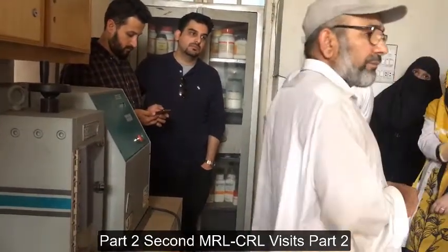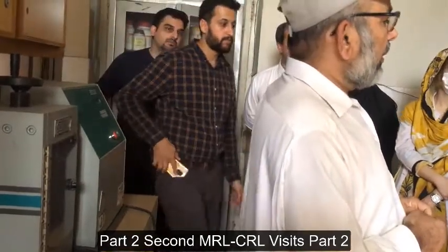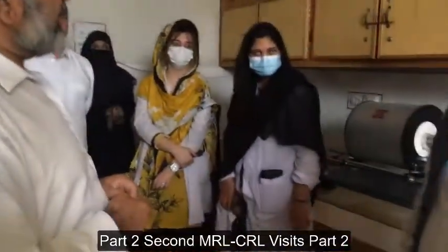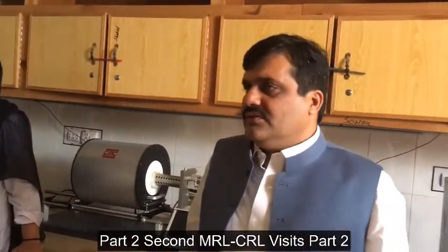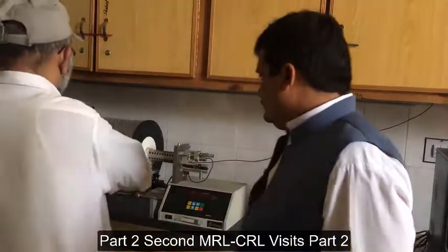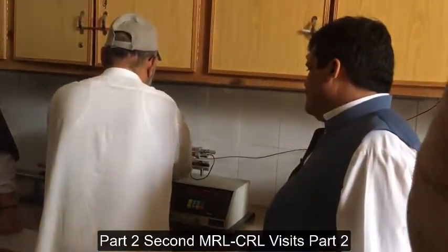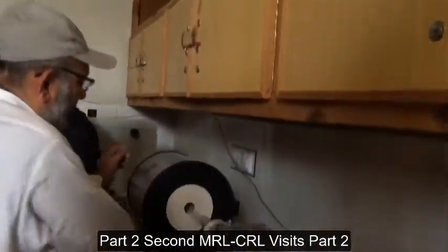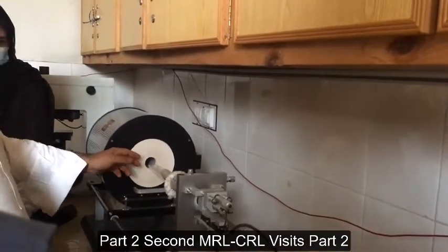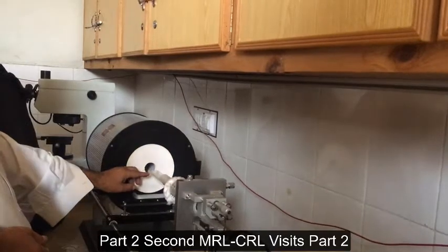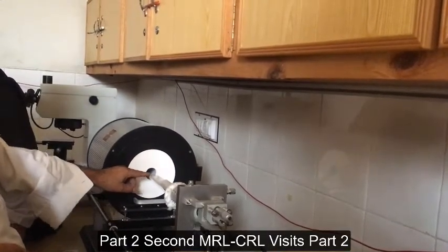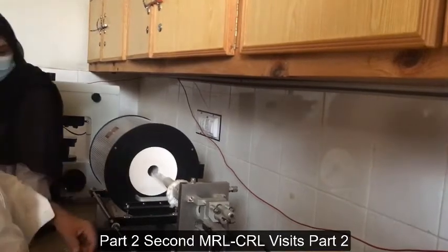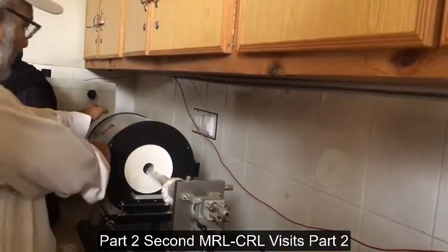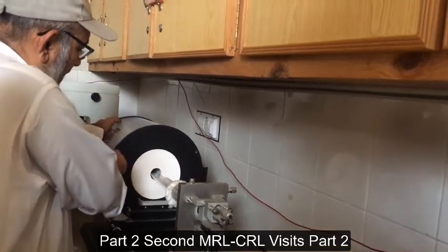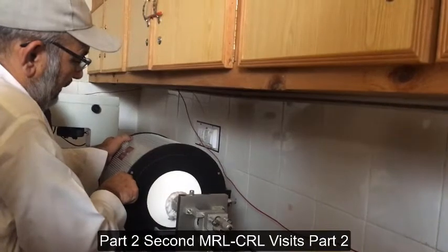Sir, for thermal conductivity, can we use this one for polymer or some other instrument? If they are not melting too much, because it has quartz crystals here. What temperature, how much? 1200. It goes up to 1200. Minimum is from room temperature. Here we put this thermocouple. It tells you the temperature of the exact sample, and there you put the sample. And when you heat it, it automatically tells you the thermal expansion coefficient of the material. This is not for thermal conductivity. This is for thermal expansion.